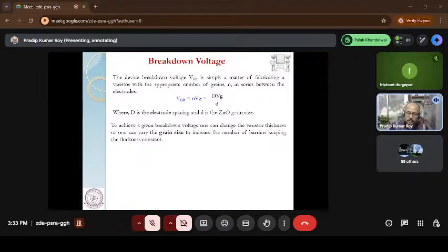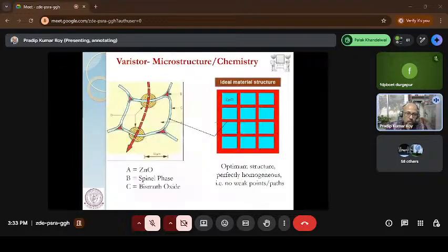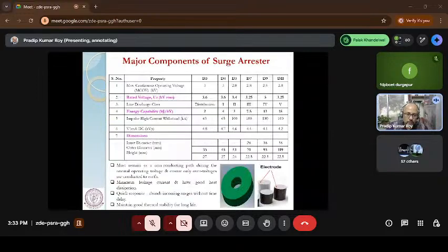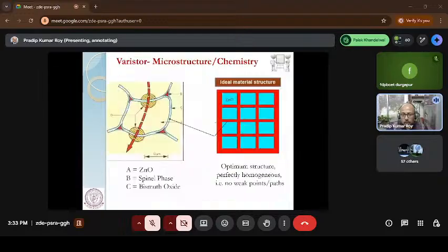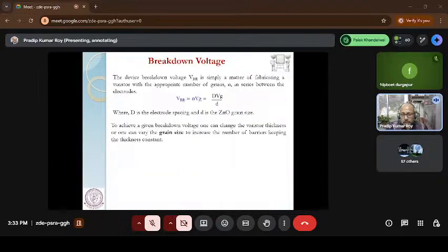Okay, so I said I would talk about the rating of the blocks. For example, if you remember the D3 blocks, I worked on the D3 block. If you look at the D3 block, the diameter is 33 and the rating of the block is 3.6. Now this rating of the block depends upon the number of grain boundaries, and to break that grain boundary, what voltage is required. So I said ideally all zinc oxide is coated with bismuth oxide.